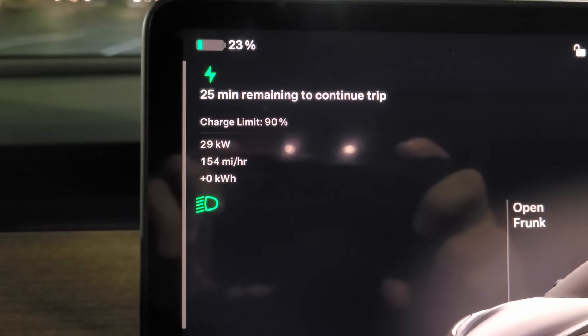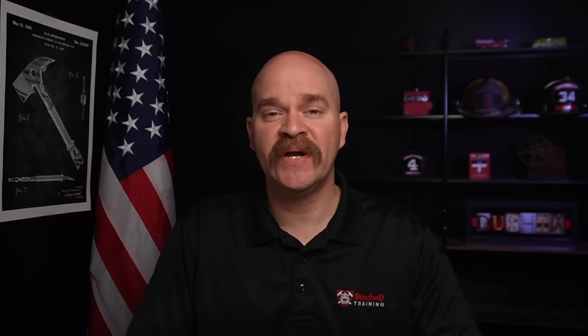Unlike an ICE vehicle, you don't want to disconnect the 12-volt battery on an electric vehicle, because that disables the battery management system and the thermal management system. You actually want those systems alive to monitor and cool that battery during transport. A good recommendation is to ship an EV at less than 30% state of charge — but is that actually happening? Especially for used vehicles, it's easy for them to arrive at the port fully charged, and a used vehicle may have prior damage from a crash, water intrusion, or poor maintenance. That creates a very real risk of thermal runaway sitting in an enclosed steel box with dozens of other vehicles nearby.